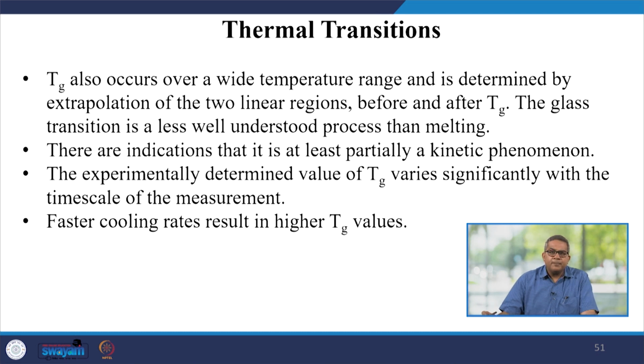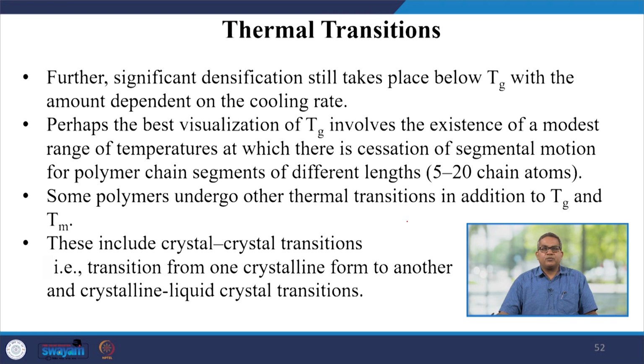Glass transition temperature also occurs over a wide temperature range and is determined by extrapolation of two linear regions before and after the glass transition. So, the glass transition is a less well understood process than melting. Now, there are various indications that it is at least partially a kinetic phenomenon, and experimentally determined values of glass transition temperatures vary significantly with the time scale of measurement. Faster cooling results in higher glass transition values.